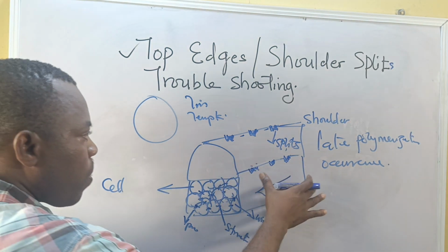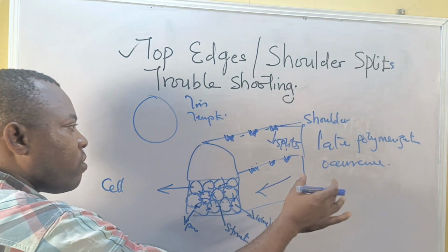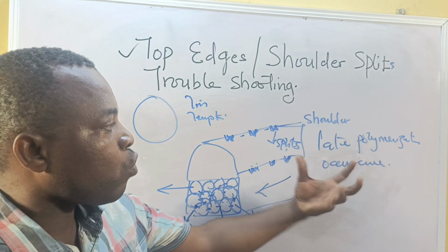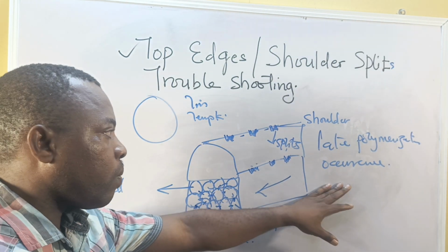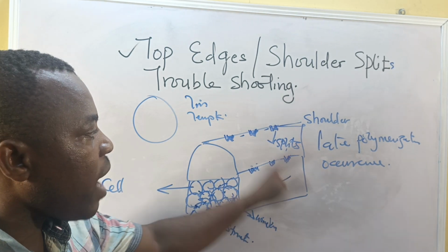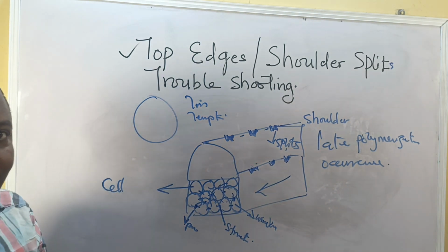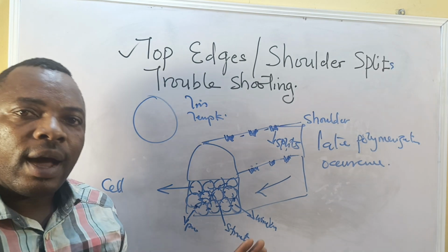But when it is too soon, what will happen? It will restrict the CO2 release. So the cell wall will suffer. It will try to release the CO2 under gas pressure, and if it could not, the internal gas pressure of the system falls below the atmospheric pressure. So in that case, the foam will shrink. So the two major effects have a negative impact on the block: split and shrinkage. So in this case, you have to balance them in proportion through the temperature and regulation of your catalyst.